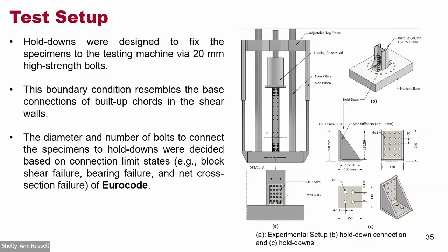The hold downs were designed according to Eurocode to take into account block shear failure, bearing failure, and net cross section. And due to the thinness of these elements, you can see there are a lot of fastener holes here in these hold downs. The hold downs material was hot rolled steel, to make them strong, and the damage didn't occur in these hold downs.